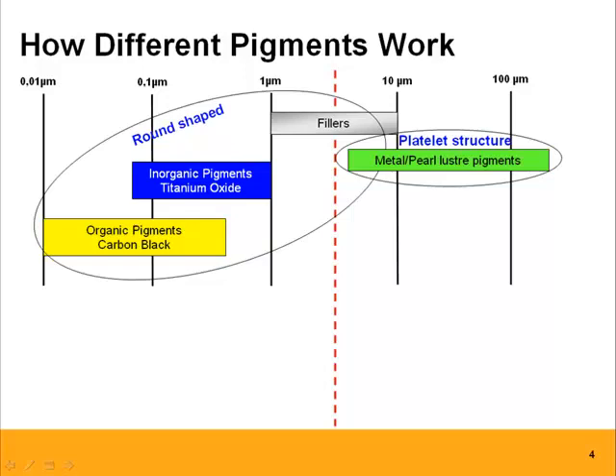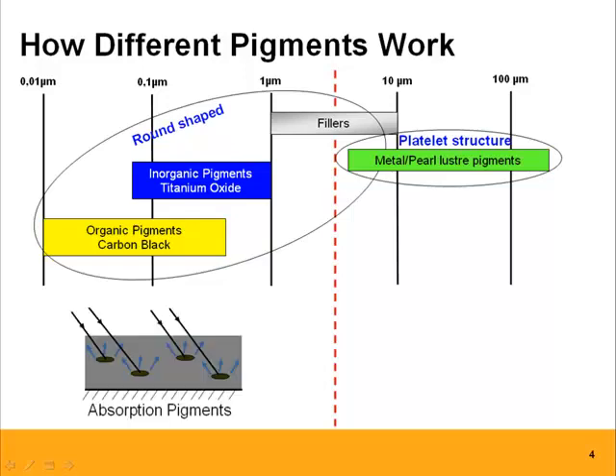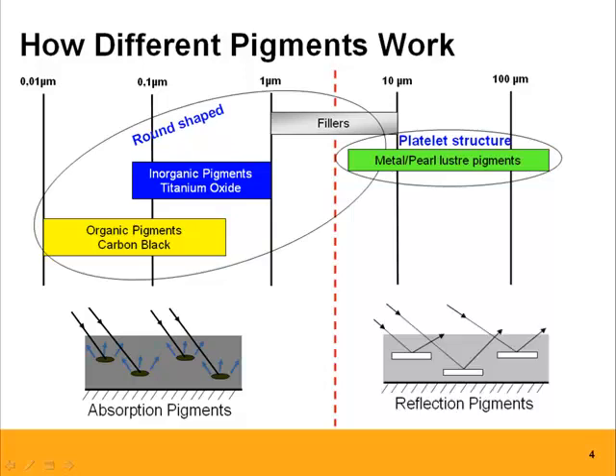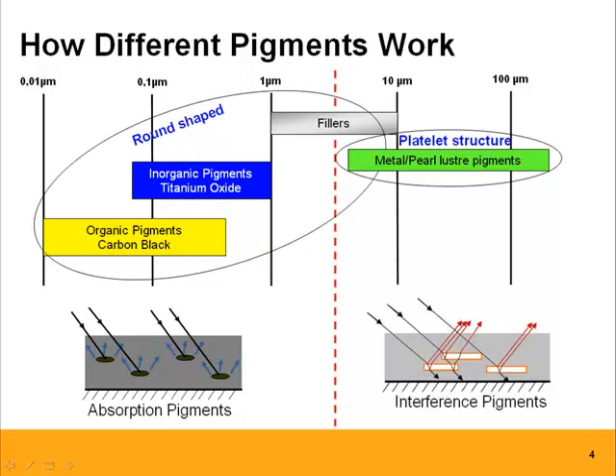And then there are the platelet-structured pigments. They're very significantly larger, in the range of 10 micrometers to 100 micrometers, and they have a real structure. Think of it as a small rectangular plate, for example, and because of that, they can act almost as mirrors. The inorganic and organic pigments react mostly as absorption pigments. They basically swallow some of the light and reflect only portions of it back, and that's what creates the color for those pigments. On the other hand, the platelet-structured pigments are reflection pigments, and they can react either as straight mirrors, reflecting the light back as it comes in, or as prisms, reflecting the light in different colors as it comes back. Those would create some of these sparkling effects that you have seen, especially when the sparkles appear in different colors.